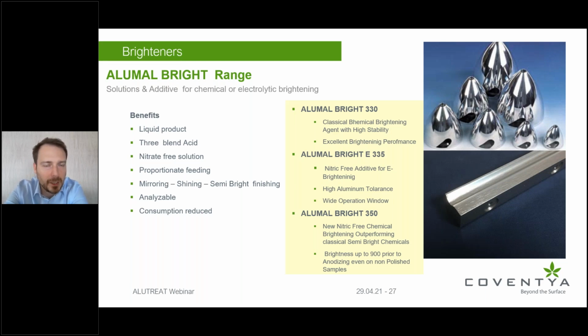which has ended about maybe 6-8 months ago, a new series of chemistry that are providing almost 50% higher gloss values than a classical semi-bright, which are nitric acid free, and they're giving, you can see from the part below, that especially on smaller and round parts, they do provide an extremely high gloss, up to 900, and that is actually comparable, especially after anodizing, with parts that are polished with nitric acid, which are not subject to mechanical polishing prior. So this is a very interesting chemistry, and we are also thinking about maybe applying for a patent for it. So that's one of the things that we will be rolling out, and even have another mini series about in the coming days to give you more in-depth information about this.